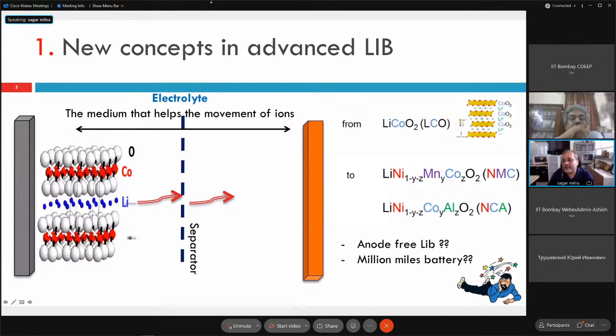What is happening during the charge? The lithium is there in the cathode side. That lithium goes out and gets deposited on the graphite side. Here, what I am doing is removing the graphite from the anode side. So lithium will deposit on this copper surface in a very thin layer, an atomic layer, and deposition will start.